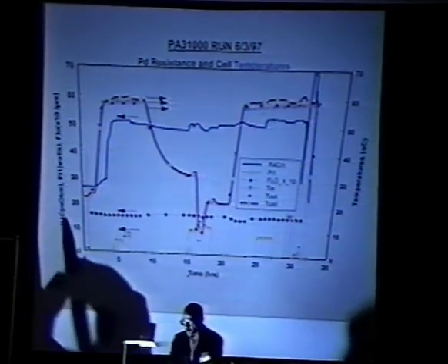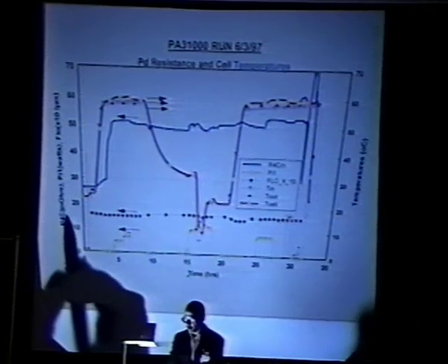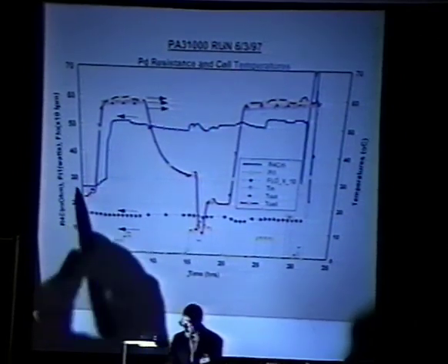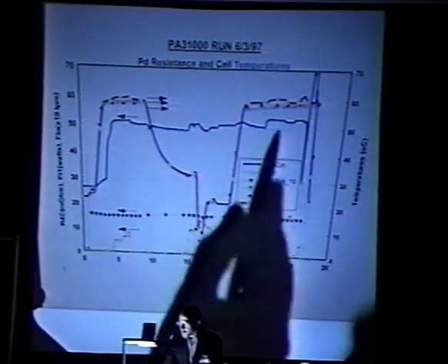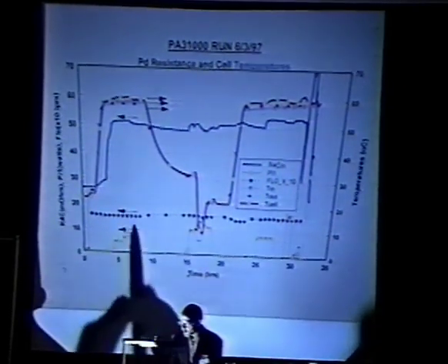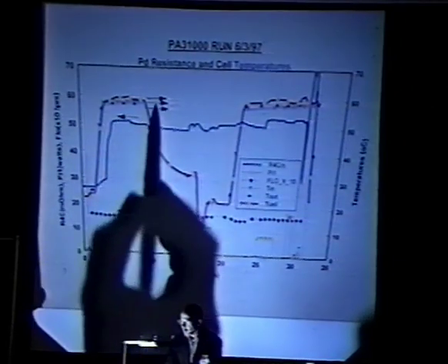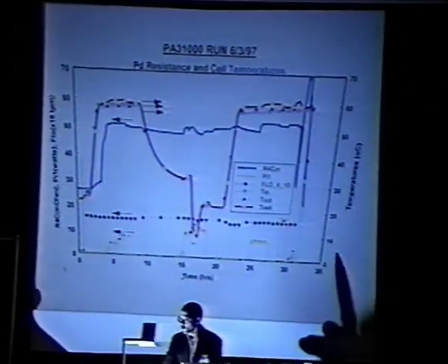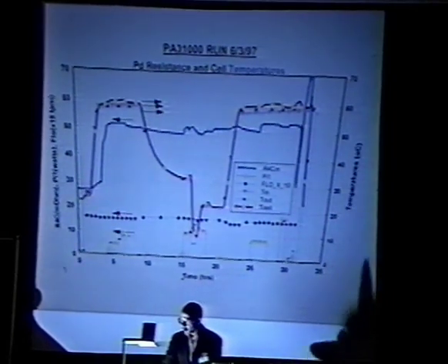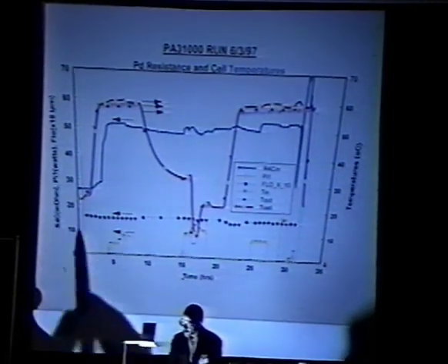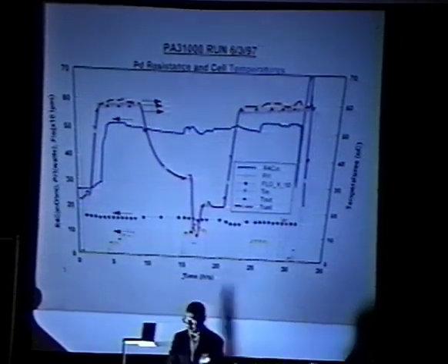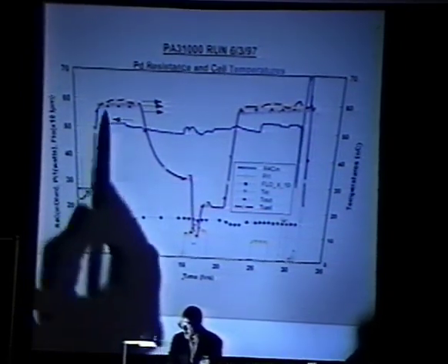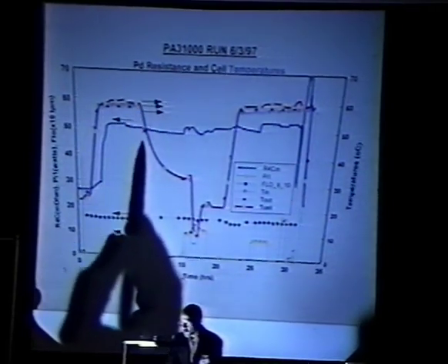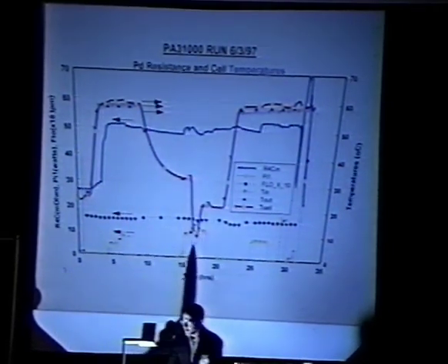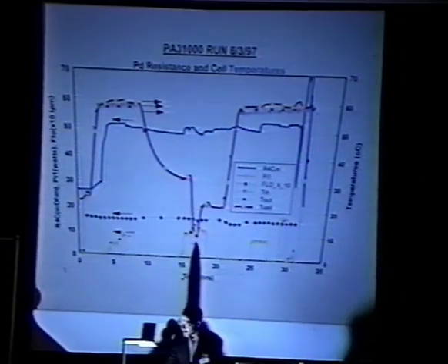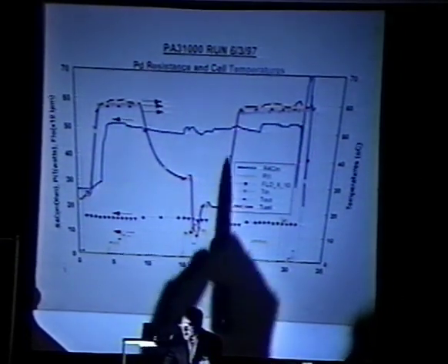What I'm basically plotting, this R4C, is the four-wire resistance across the palladium. And so if you're interested in loading curves, this dark blue is essentially the resistance of the film. And these arrows then point to which scale we're looking at. All the temperatures are plotted over here on this right scale. So for this particular run, for example, if we just look at the temperatures, this thing over a 35-hour period started down here, the temperatures go up. Then I basically let the system drift and cooled it way down to about 9 or 8 degrees centigrade, and then heated it back up, and then heated it up again with the ramp.